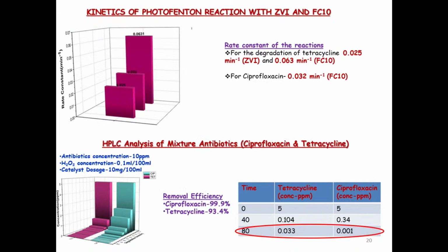But in reality, when you go for real samples, you don't have a single antibiotic there. You have a mixture of antibiotics. So you should have a material which should be able to act on any number of antibiotics. We have limited our study in this case to ciprofloxacin and tetracycline together, and both of these can be simultaneously degraded using the same material, up to about 99.9% and 93.4%. You can also see that the rate constant of the Fe-Cu heterostructure is almost 3 times that of ZVI itself, and the same holds for ciprofloxacin degradation also.